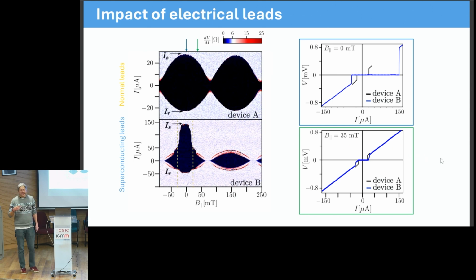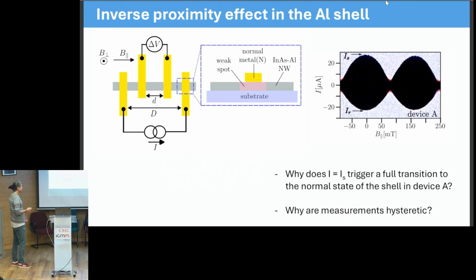So what has happened here? Well, the critical field of our superconducting contacts is of the order of a few 10 millitesla. So for fields larger than this 35 millitesla, which is shown here by this dashed line, the aluminum contacts that we deposit are also normal. So when the superconducting contacts turn normal, we also see that this inverse proximity effect takes place. Okay, so that's the idea. It's a kind of simple thing, and actually, one would wonder, why not expect this? But indeed, as I said before, this was completely overlooked.